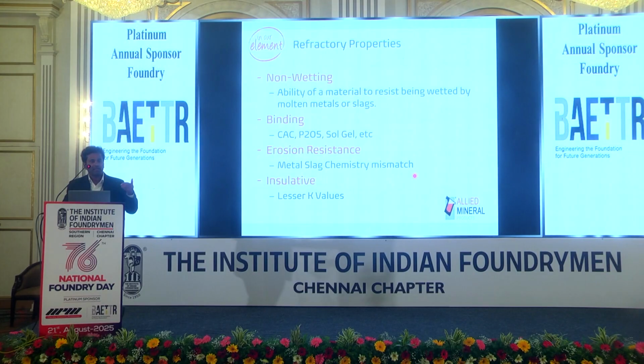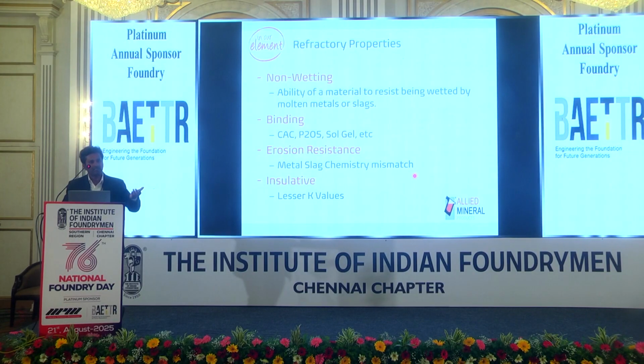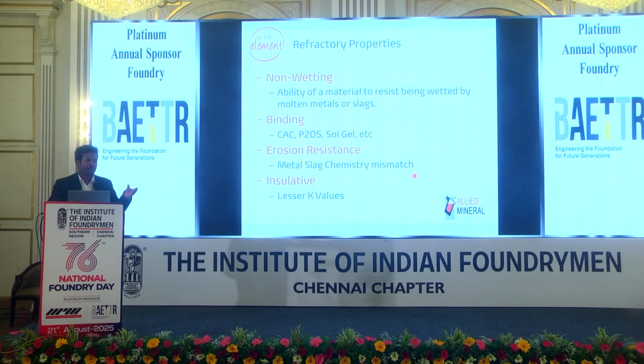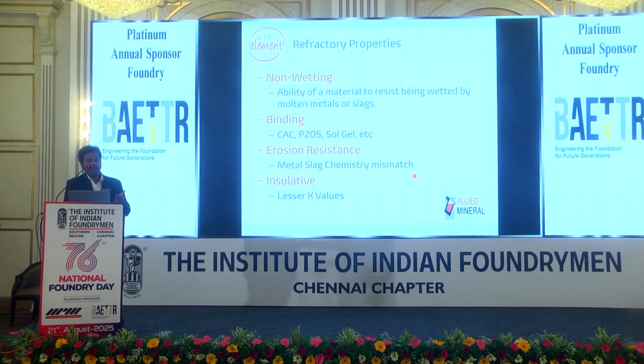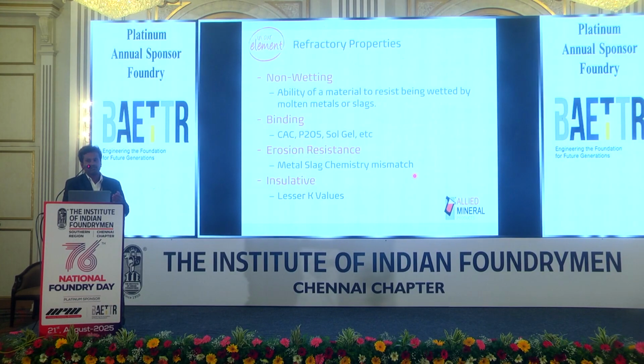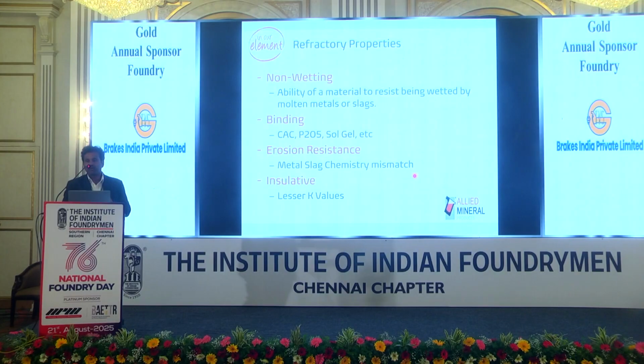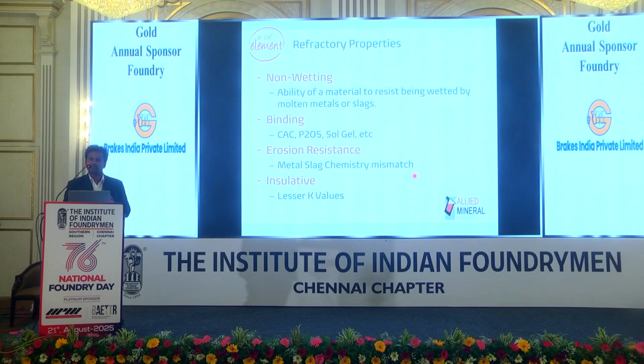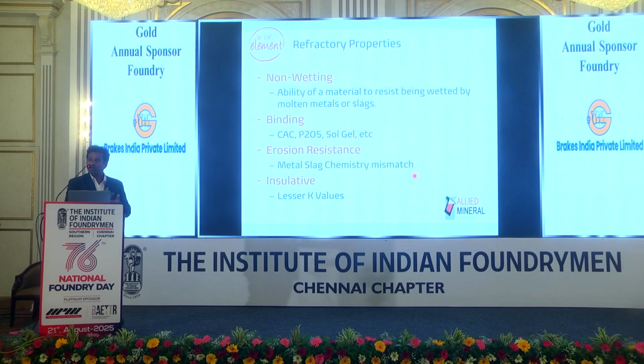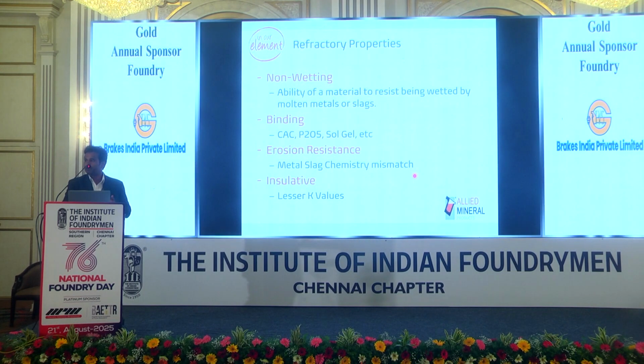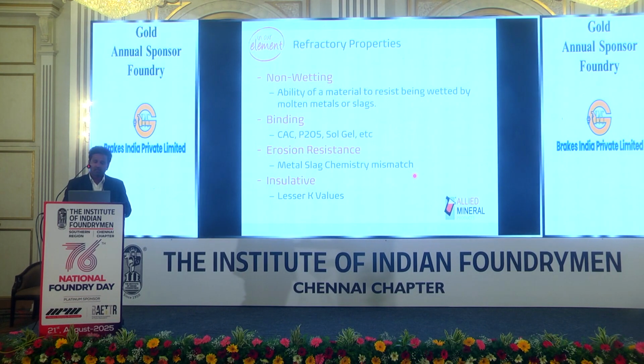You cannot again use the calcium aluminate system for patching purposes, because already fired, dried refractory will not adhere with the new castable system. So in that particular case, you have to use a phosphate bonded system, which will adhere to the old dried refractory in a much better way compared to the calcium aluminate cement system.